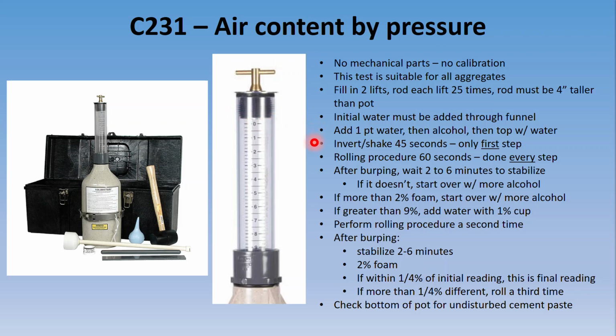Your first step, you saw this in the video, is to pick this thing up, invert it, and shake it for 45 seconds, inverting it no more than 5 seconds at a time. And you only do this step this very first time. You don't have to perform this step a second time, and that's something that trips people up. They'll want to do this on their second round as well, but you only invert it once. We're not going to make you do it 45 seconds in the actual practical tests. We'll make you do it for maybe 5 seconds, and then we'll ask you, how long do you do this for?